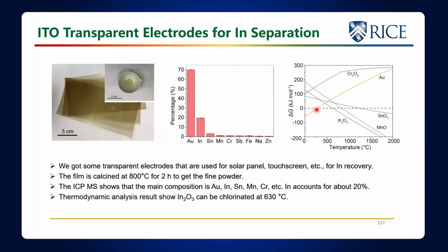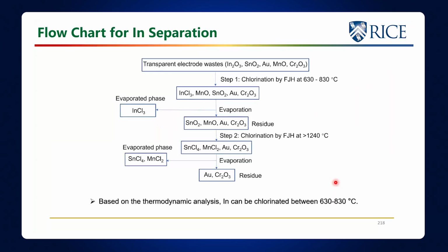So gold, we're going to have to go after in another way. But anyway, we can get the indium out. As long as we just heat it quickly to this region, only indium should come out. The manganese shouldn't come out until you get much higher, up here. So hopefully we can just heat it up to right in this region and pull out the indium. So we want to take this mixture, which has indium oxide, tin oxide, gold, manganese oxide, chromium, and do the chlorination. We would get indium chloride, and the other compounds would remain as the oxides.